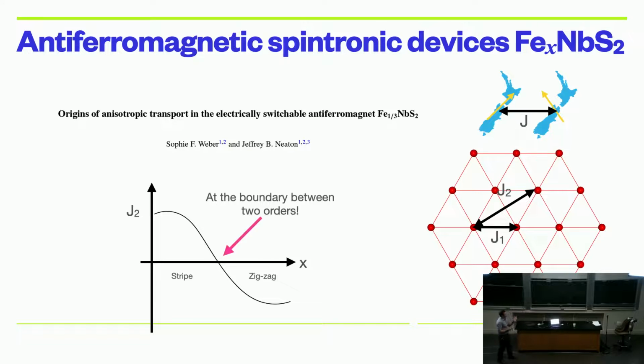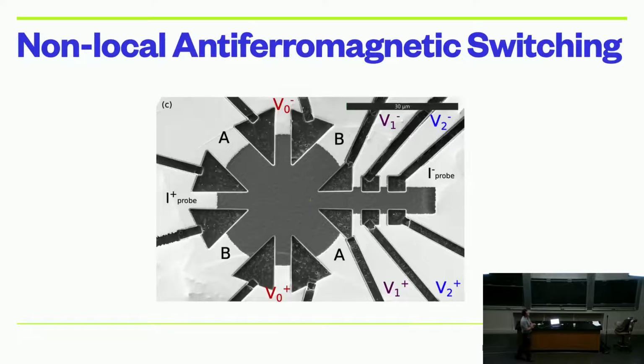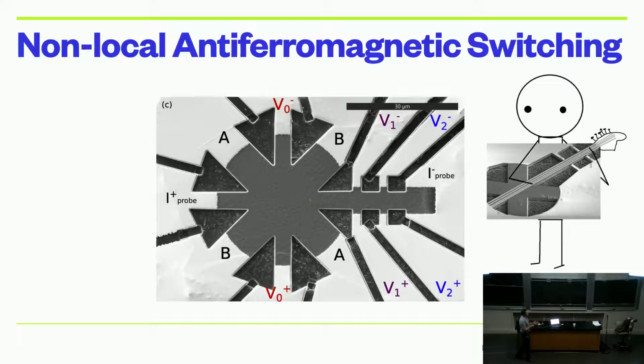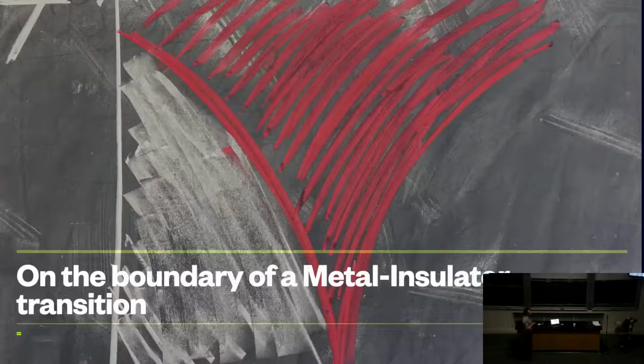And that's with a totally, okay, so boundary between two orders, but it's not exactly a boundary of critical points. I'll skip this bit. Well, you can actually extend these arms of these devices, and you can switch the signal 30 microns away from where you're applying current. So there are these non-local effects as well. Whatever is happening to the domain boundaries, it's extremely effective, and it's propagating them tens of microns away from the active area where you're applying current. So I think it's something quite neat, much more effective than other systems.